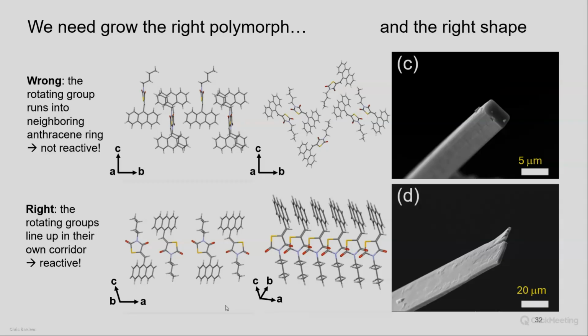So for example, I talked about azobenzene at the beginning of the talk. That molecule in solution loves to do cis-trans isomerization, but in the crystal it's completely dead. It doesn't do any photochemistry in the crystal, and that's because it's packed too efficiently. So it helps to have some extra stuff that opens up some room inside the crystal and allows whatever group needs to change its geometry to rotate or do whatever it needs to do the isomerization. For the anthracenes, again, I didn't talk about it, but packing is key. You have to get the anthracenes close enough so they can undergo the intermolecular interaction. So polymorphism is totally important, and you can have a molecule that's very reactive in solution and completely unreactive in the crystal. Then you have to get to work and try other crystal polymorphs and see if you can get it into a geometry where it can react.